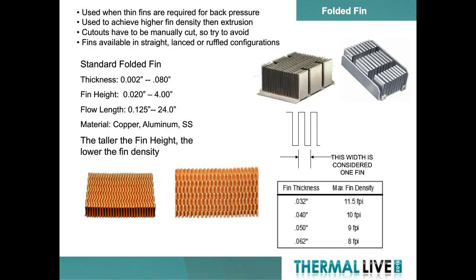So what we introduce is a folded fin solution. The fins can be made out of aluminum, copper, stainless steel as common materials. Looks like the interior of a piece of corrugated cardboard. It is a continuous sheet of metal that is stamped and folded into the required shape. Fins generally range from 2/1000 up to 80 thousandths of an inch. Most customers use 10 to 15 thousandths. So they're getting something that is significantly thinner than what you can extrude.